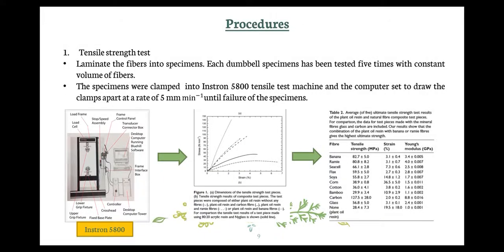For the procedure, first they conduct the tensile strength test. So they laminate the fibers into specimens. Each dumbbell specimen was tested 5 times with a constant volume of fibers. And then the specimen was clamped into the Instron 5800 tensile machine, placed in here, and the machine pulls the specimen until it breaks, and then the software and the computer record the result.